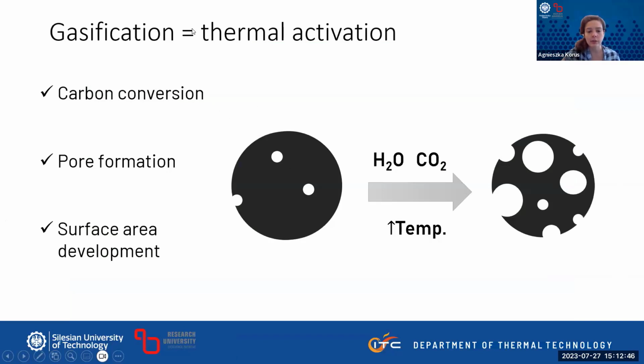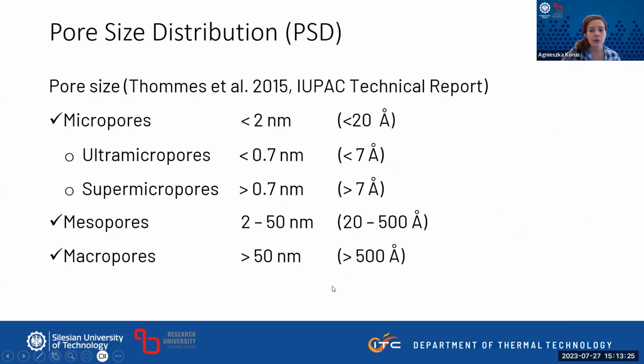Because as you all know, gasification works a little bit like a thermal activation of the carbon. You can get more porous particles, and the porosity of the carbon used for flow electrodes is quite an important, or one of the most important, aspects of the working electrode. At least it's considered one of the most important aspects. So this was the feature that we wanted to focus on in our preliminary studies about the material that we want to use.